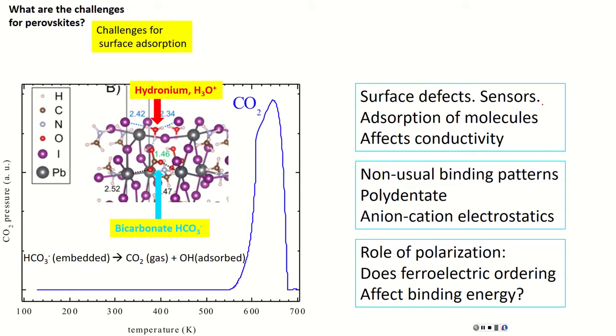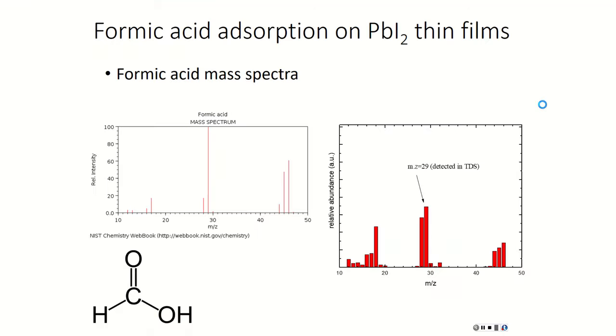This is a project going on in collaboration with Dr. Burkhaus. The surface of so-called hybrid halide perovskite can be covered by different ligands, and one directly measures the binding energy by thermal desorption, looking at which temperature the ligand desorbs into vacuum when one heats it. And by assuming mechanisms of co-adsorption and different binding sites, one can find computed energies close to what is observed in experiment.